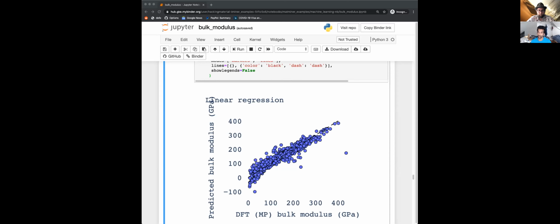We've done some benchmarks on transition metals, and the behavior for the primary peak isn't too bad with the limited benchmark sets that we were able to find. Cobalt oxide, iron oxide, those kinds of systems. But if you want very precise X-ray absorption spectra, this isn't the data set for you. You need to compute your exact situation. That's another thing, is that this is general, it's perfect materials. There's always going to be deficiencies, but they're good enough for a lot of purposes.